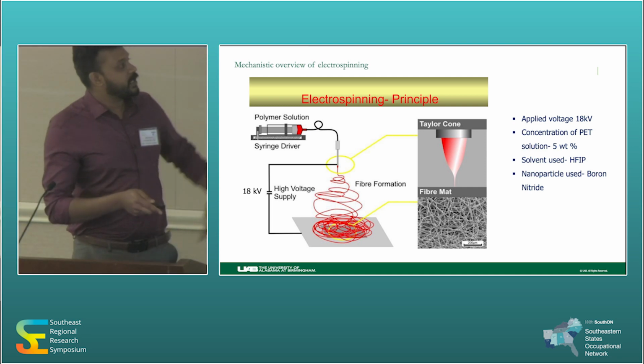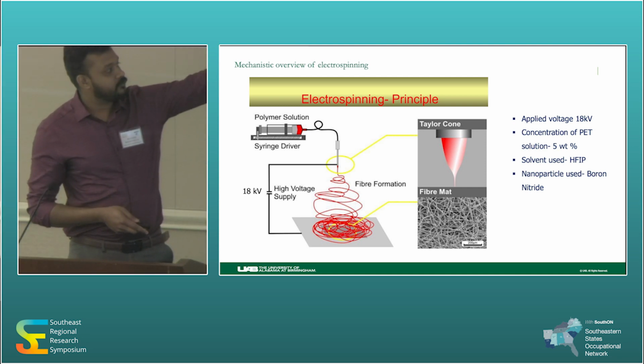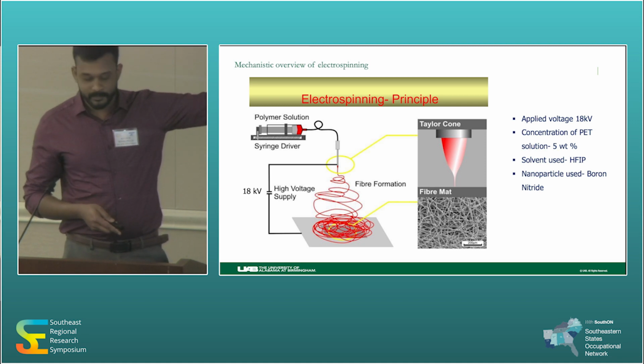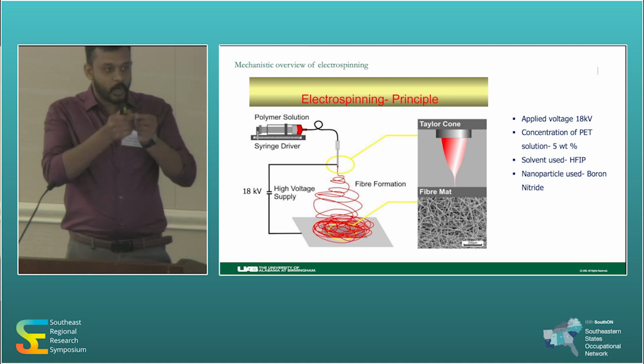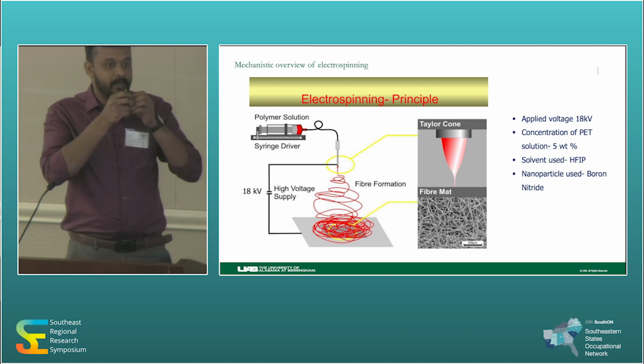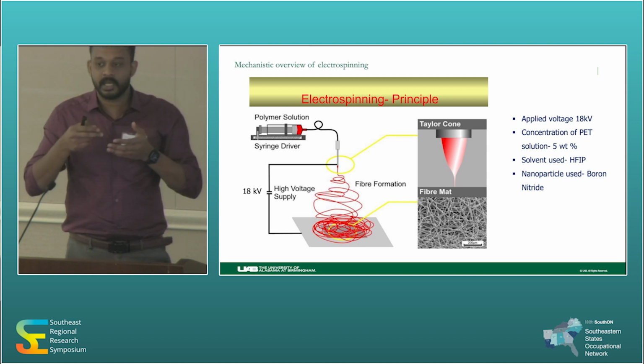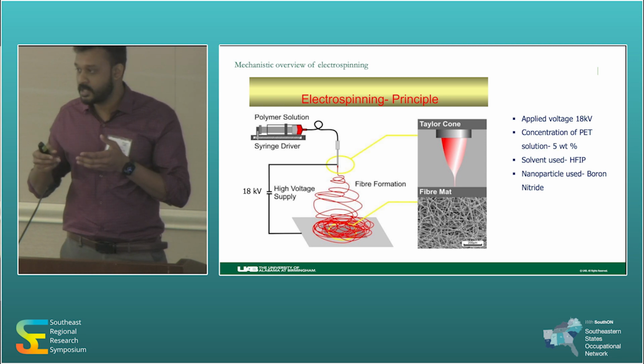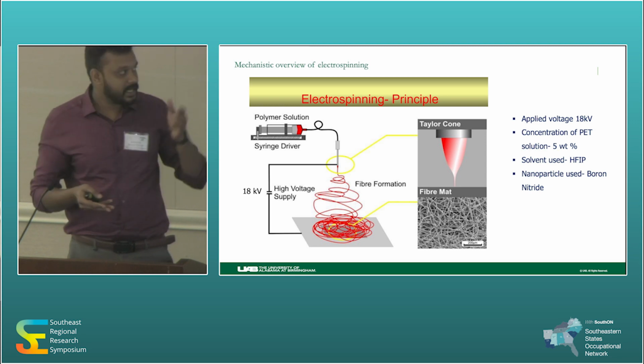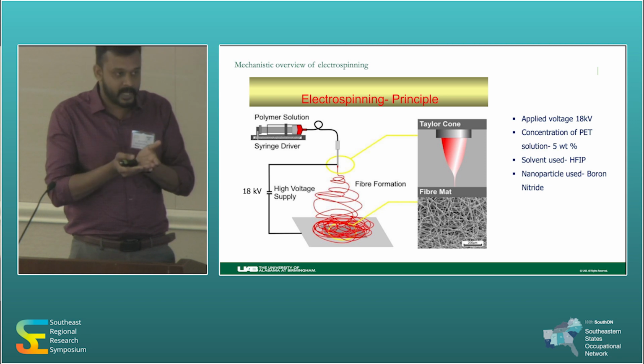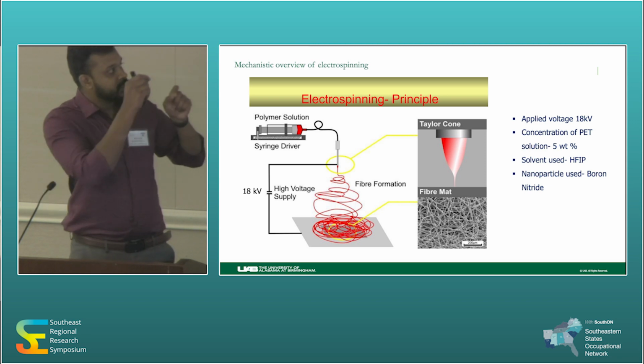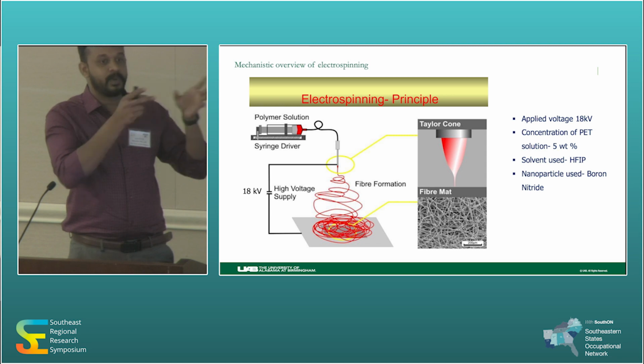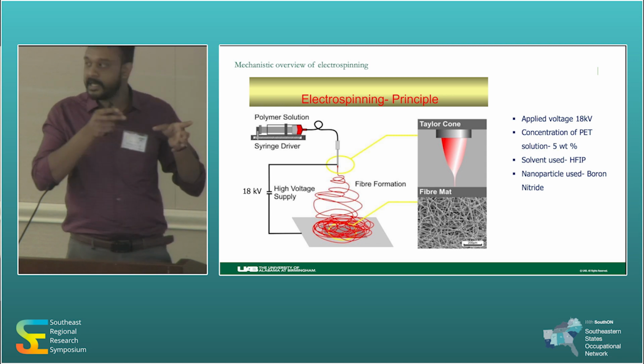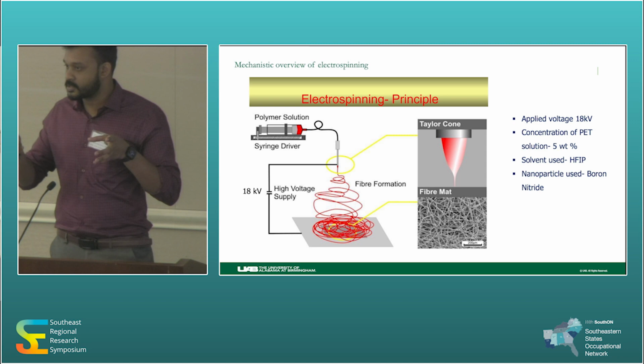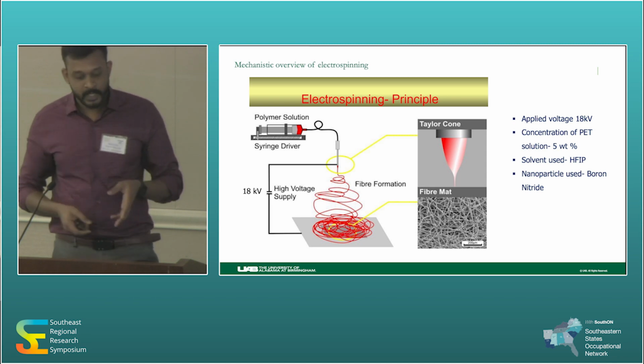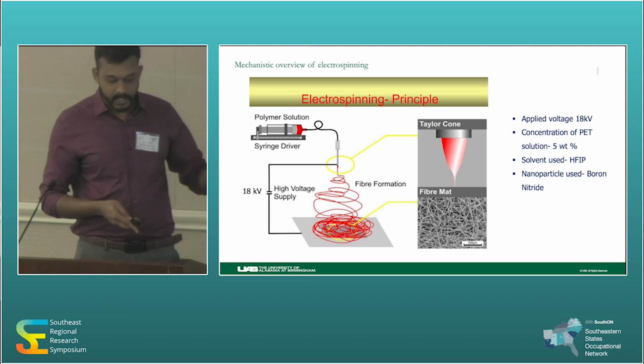So in electrospinning, we use a polymer solution and apply a high electric potential. With that potential, the droplet at the needle tip is blasted and deposited as non-woven fibers on top of whatever substrate you are using. In our case, we are using just fabric. So on top of the fabric, the polymer solution is deposited as non-woven nanofibers. That's the second technique we used in this study.